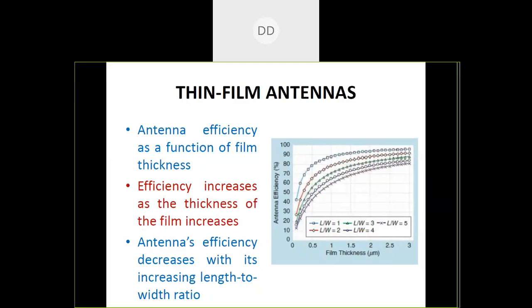The next point is antenna efficiency as a function of film thickness. From this diagram, we can see that efficiency increases as the thickness of the film increases. But the antenna's efficiency decreases with its increasing length to width ratio. So there are two parameters which have been studied from this graph. We can observe that antenna efficiency increases as the thickness of the film increases. But we have earlier seen that as the thickness of the film increases, the transparency level will decrease. So this is a trade-off, whether we want a more efficient antenna or a more optically transparent antenna. Also, the length to width ratio of the antenna affects the efficiency. Even for the same thickness, if the length to width ratio is more, then the antenna efficiency will be less.